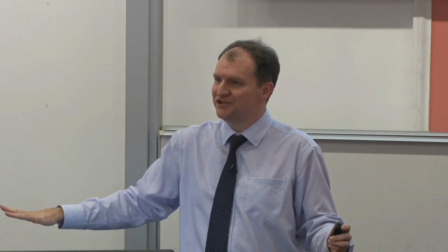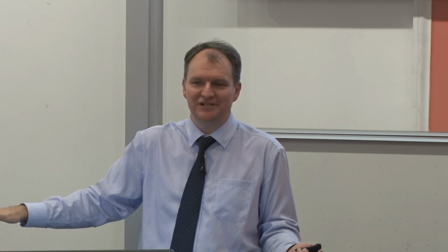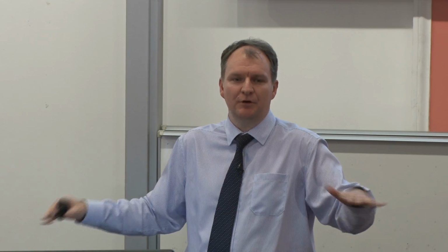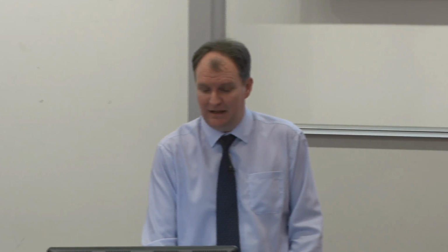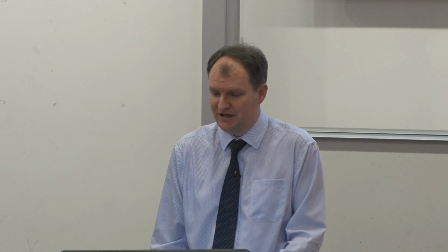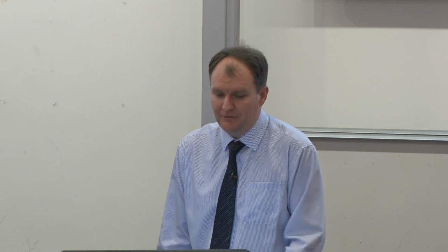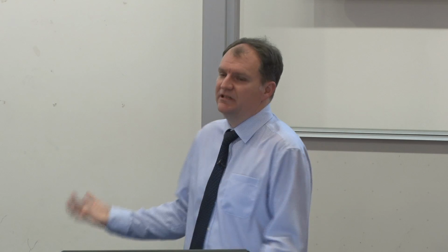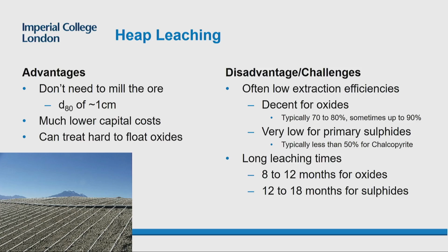You then have an impermeable layer at the bottom, and that's one of the other changes in the way it's operated. Historically, heap leaching had a bit of a bad reputation because of its potential for polluting groundwater, etc. But modern ones have a good impermeable layer at the bottom. You collect the material that comes out, which will hopefully have a lot of copper sulfate in it, and then you recover the copper from the copper sulfate via solvent extraction and electrowinning. The big advantage is that you don't need to mill the ore. The particle size is maybe centimeter-size particles.